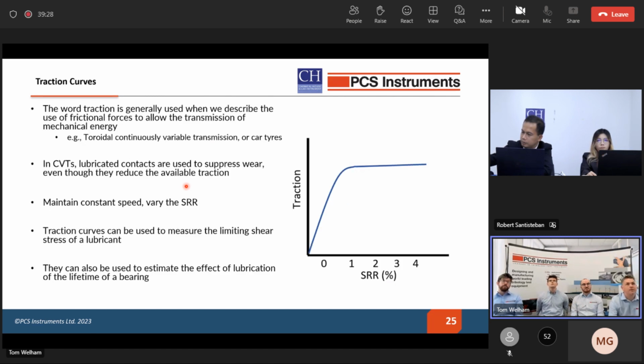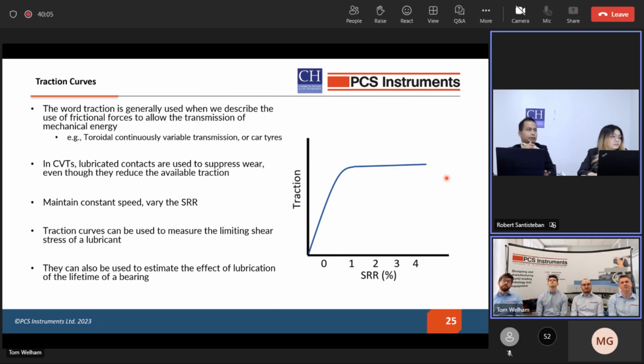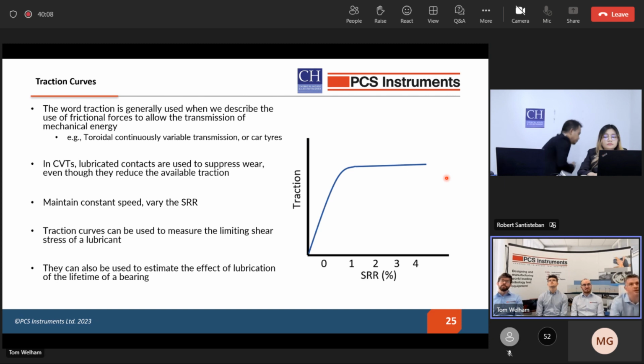So traction curves are also very useful. We usually use the term traction to describe the use of frictional forces to transmit mechanical energy. So as mentioned, in this type of step, we fix the entrainment speed, and then we vary the proportion of sliding to see how traction is impacted. There are many benefits to looking at this, one of which is to look at the limiting shear stress of the lubricant. It's particularly useful in CVTs as well, where we're using the lubricant with the aim of transferring a force using the contact.